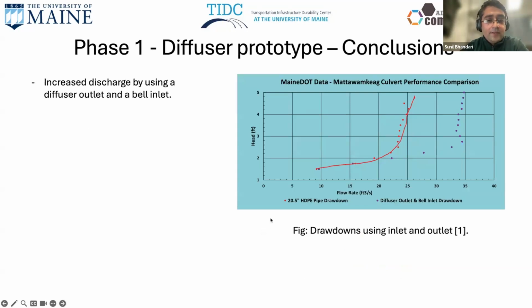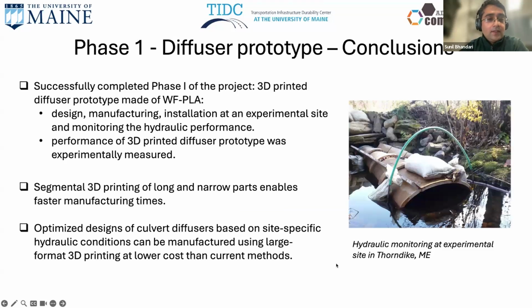And based on the measurements done at the Thorndike site, it showed that the flow was increased by about 40% based on the water levels, comparing just the HDPE pipe and the HDPE pipe with diffuser outlet and bell inlet. So for phase 1, we successfully completed phase 1. We designed, manufactured, installed the 3D printed diffuser at the site and monitored the hydraulic performance.